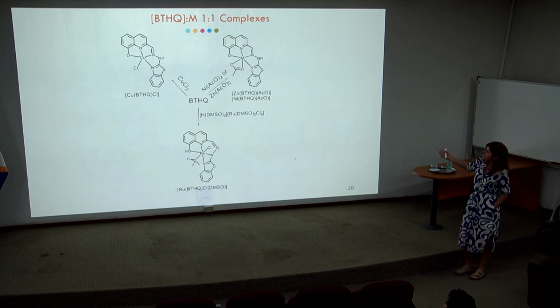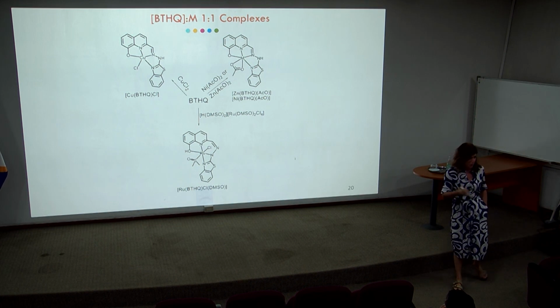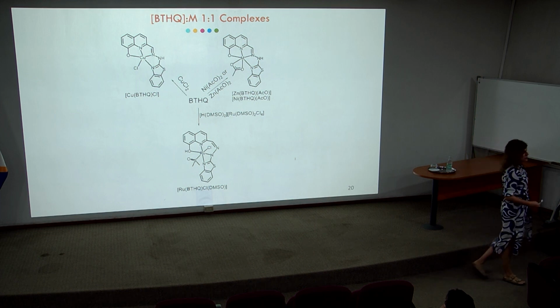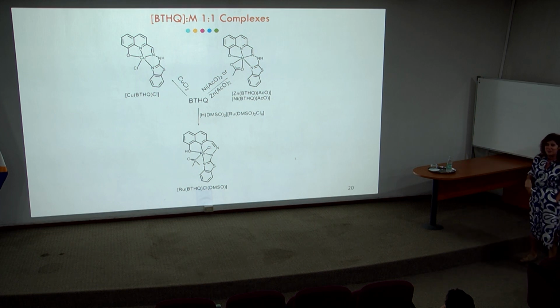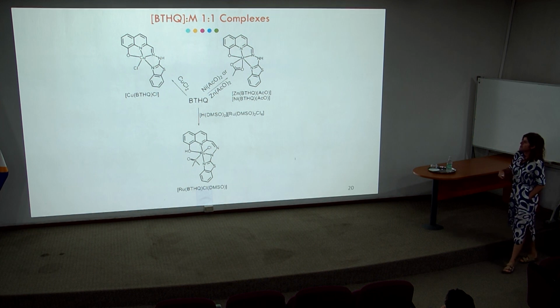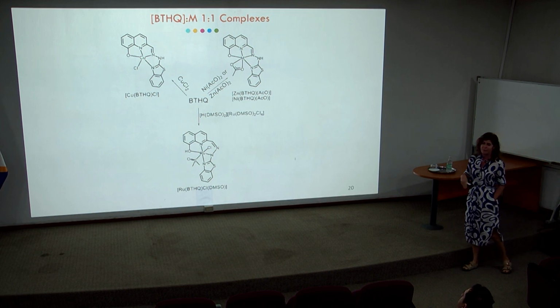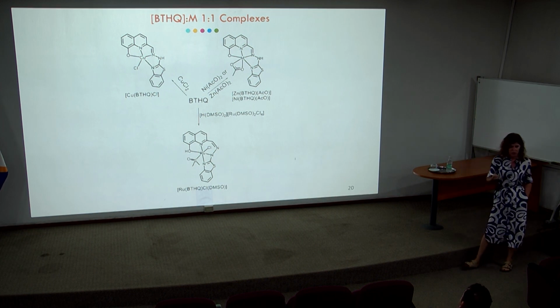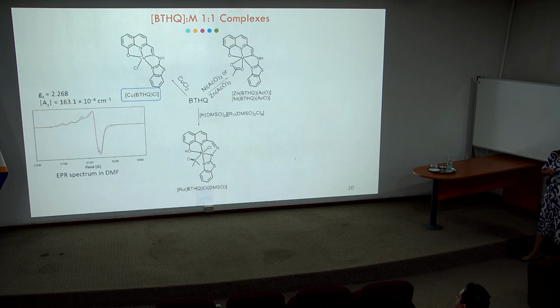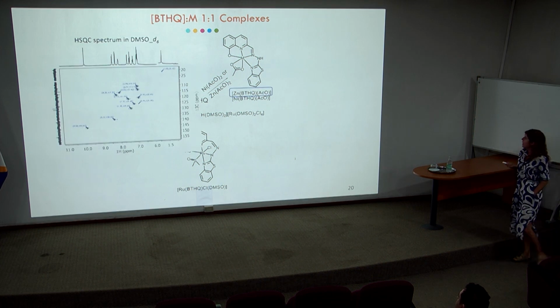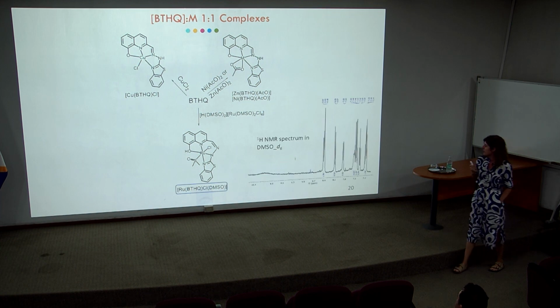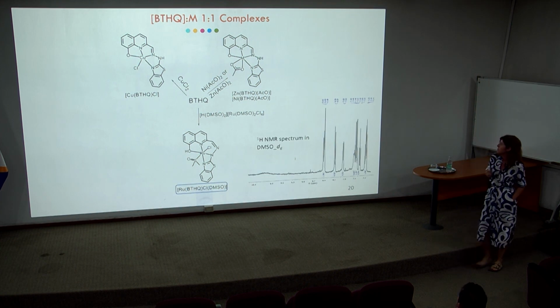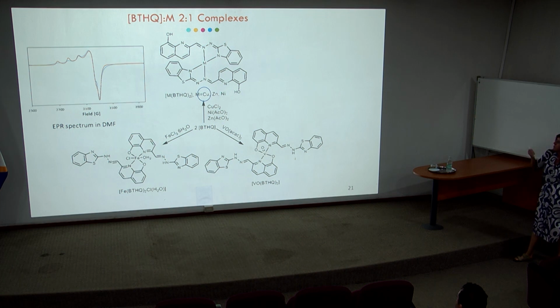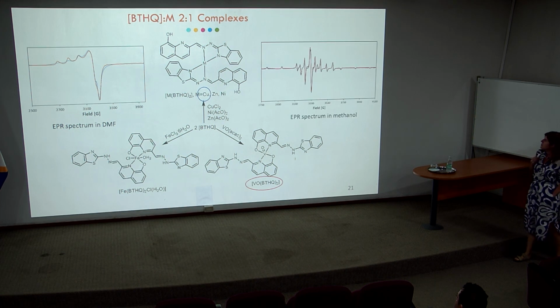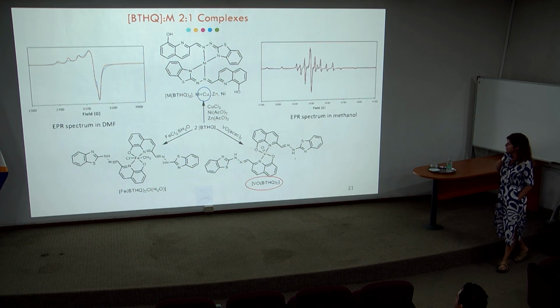Of course, these are a lot of compounds. We were not able to obtain X-ray structures for this system. It's not easy to crystallize it. But we did a very extensive spectroscopic characterization of the system, EPR for copper, NMR for zinc and nickel, and also for ruthenium. The same for the 1-to-2 complexes, EPR for the copper and vanadium.